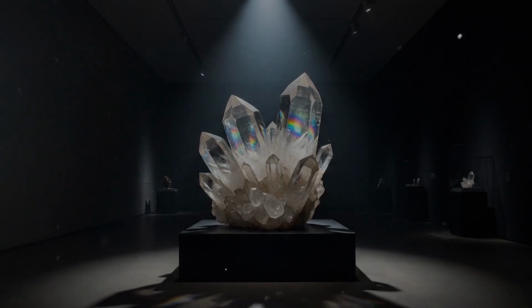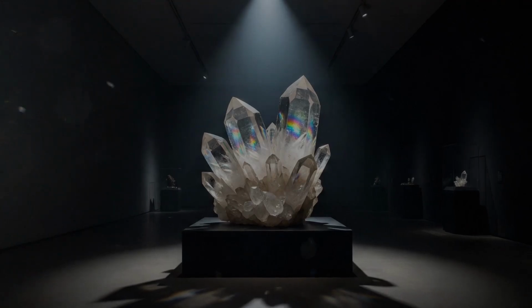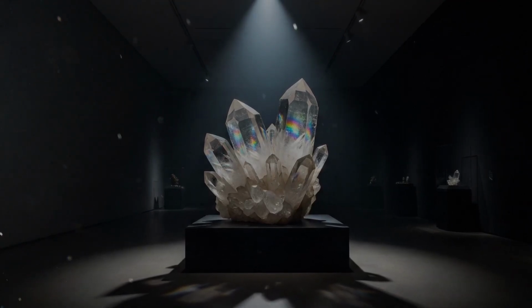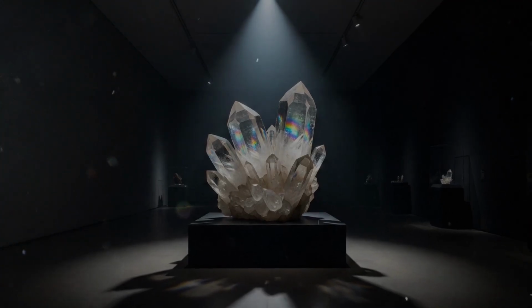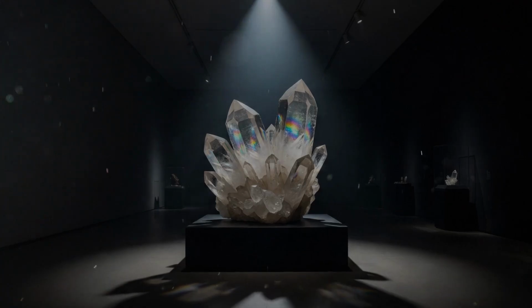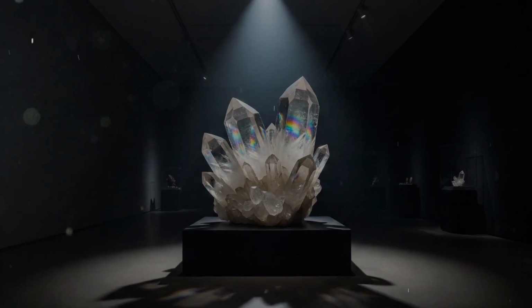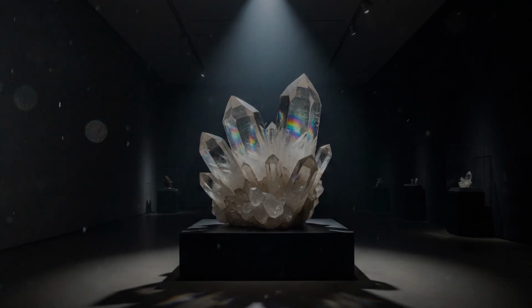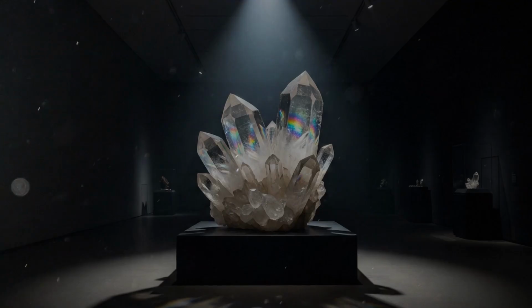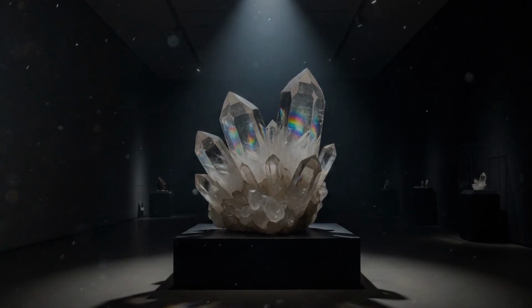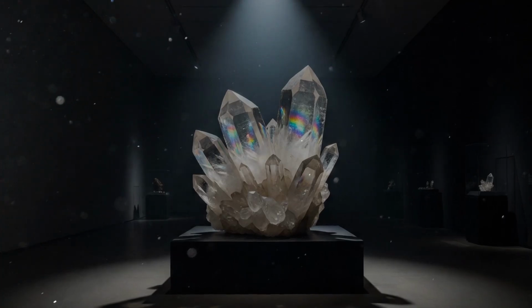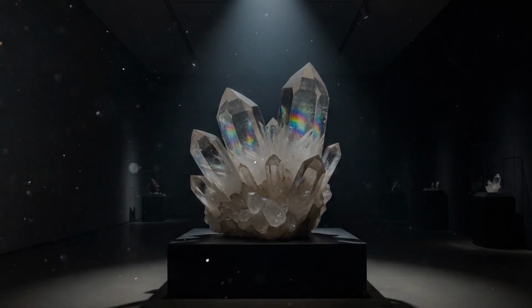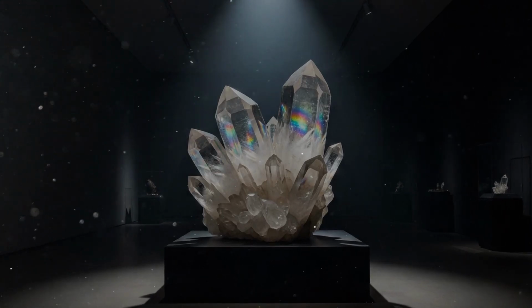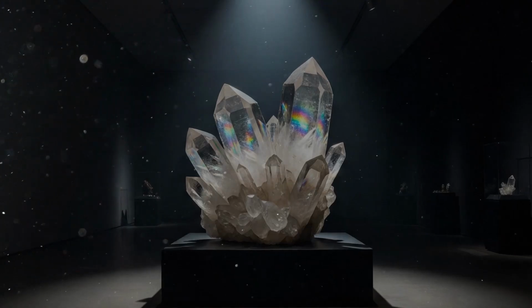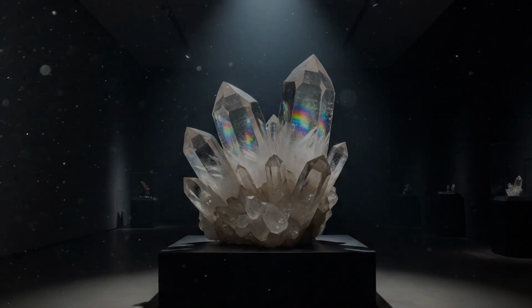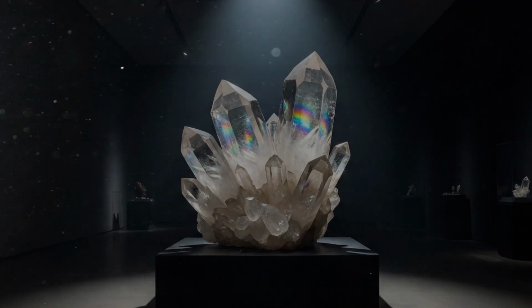Laboratory experiments have measured hydrothermal crystal growth, and under ideal conditions, quartz can grow about 0.4 to 1 millimeter per day along the Z direction, the direction perpendicular to the crystal's long axis. This might not sound slow, but remember that crystals forming in nature rarely experience ideal conditions consistently. Growth rates fluctuate with changes in temperature, pressure, and solution chemistry. A crystal might grow relatively quickly for a period, then growth might nearly stop, then resume. The history of these changing conditions is sometimes recorded in growth zones visible within the crystal.